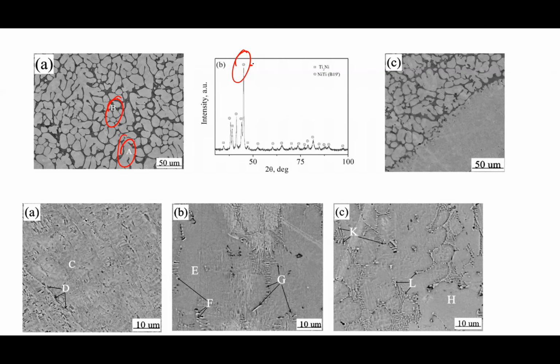Whereas when we closely observe the SEM images of the layers on the second, third, and fifth, it shows the presence of columnar grains in the inner layer having an internal dendritic structure. This is similar to the first layer, with similar size of dendrites and interdendrite space. This also shows a kind of secondary layer with a large volume of gray space, where small dark gray dots are distributed through the whole volume.